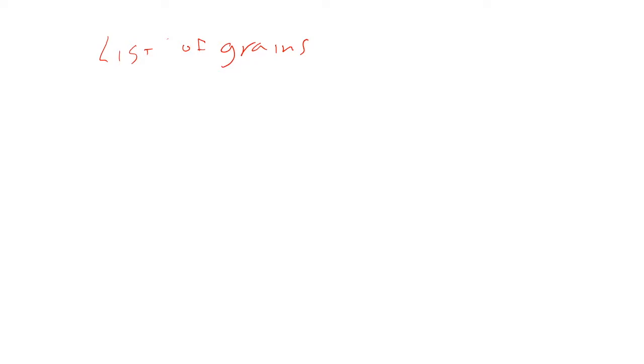And that's specified by their orientation and volume fraction. How big it is, right? You can just take this right from EBSD. You get the orientation of the grain and the weight in its area in either pixels or an absolute size, depending on how you calibrated your EBSD scan, right? And you can just put those weights in directly.